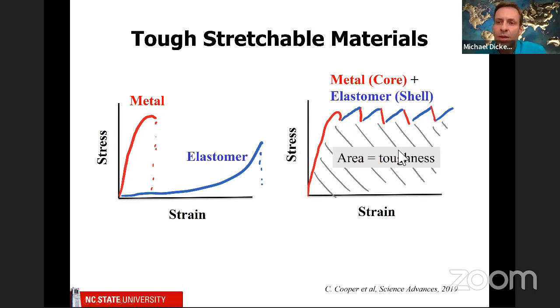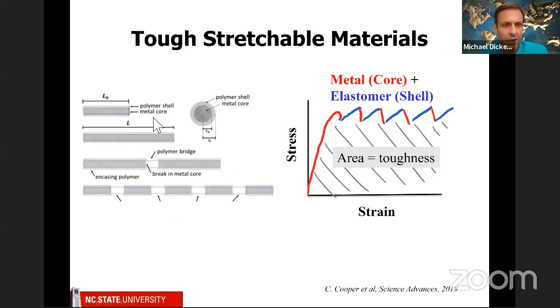And the reason you want that is the area under that curve is toughness. You think about force times distance is energy. Well, same thing, stress times strain is energy, which is just the area underneath this curve. Okay, so how do we do that? Well, it's really simple, actually. We take an elastomeric tube, we put in liquid metal and we freeze it. We use gallium because you can actually freeze it at room temperature.